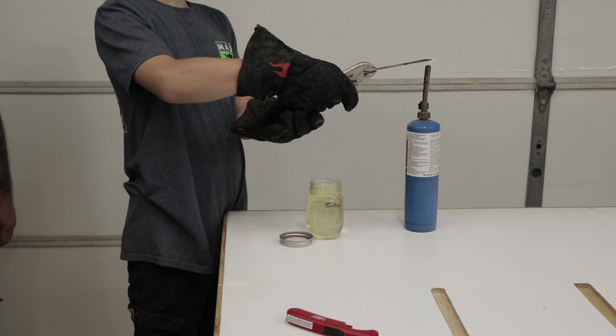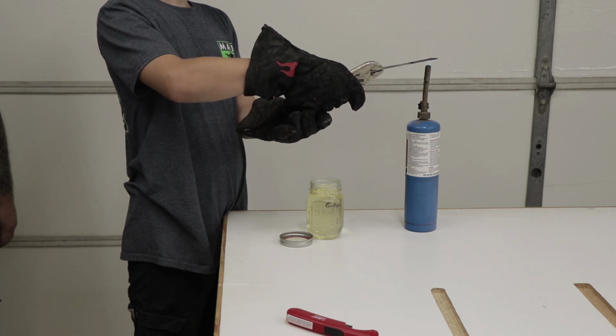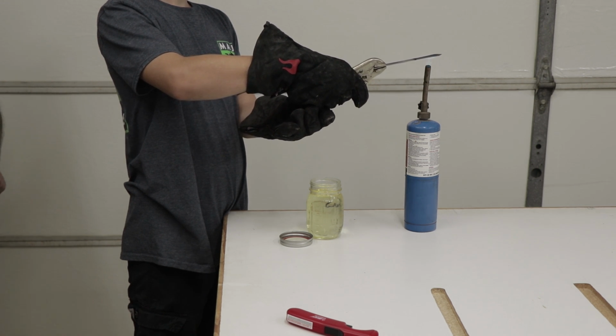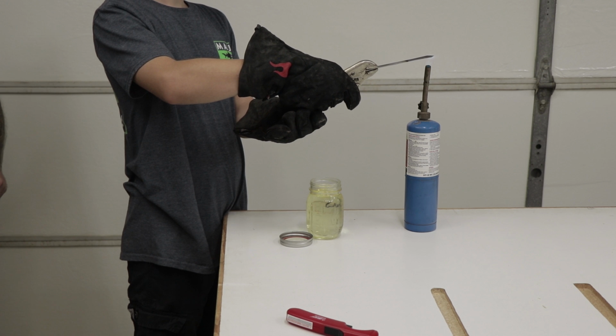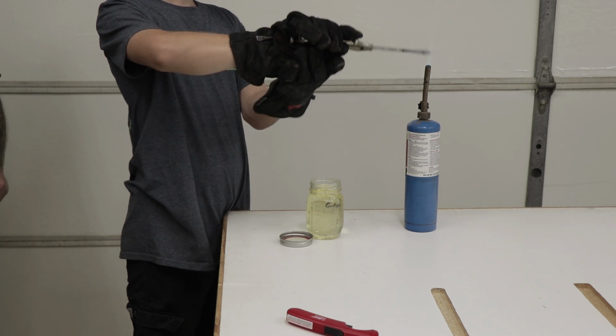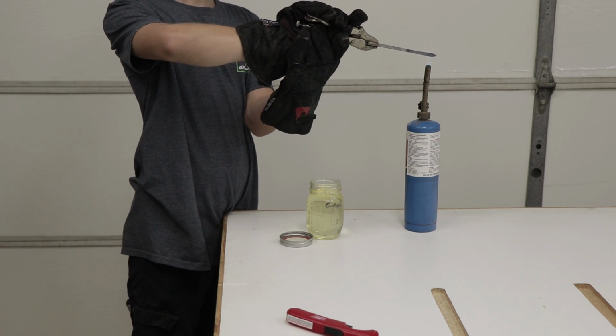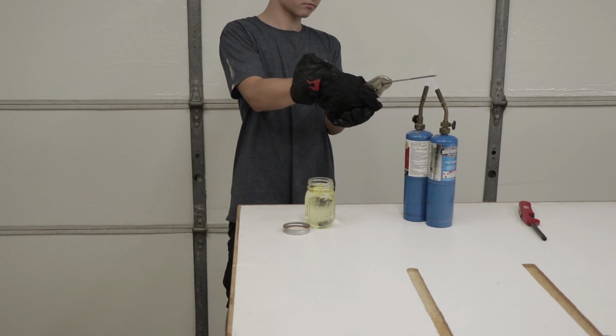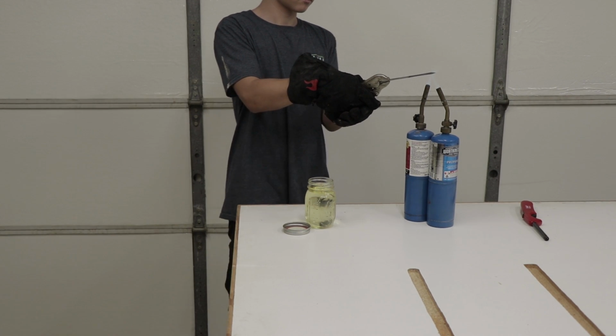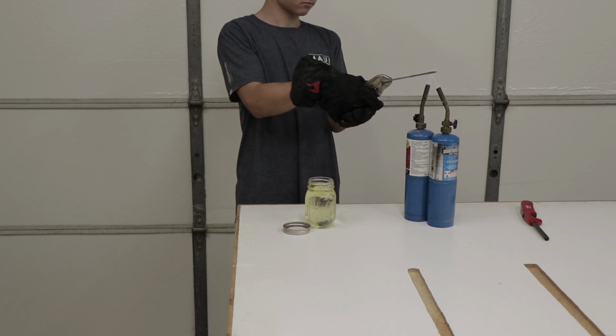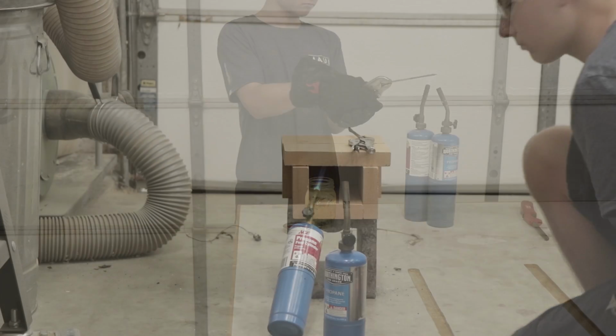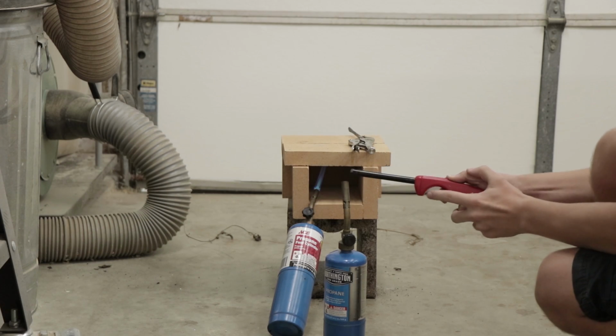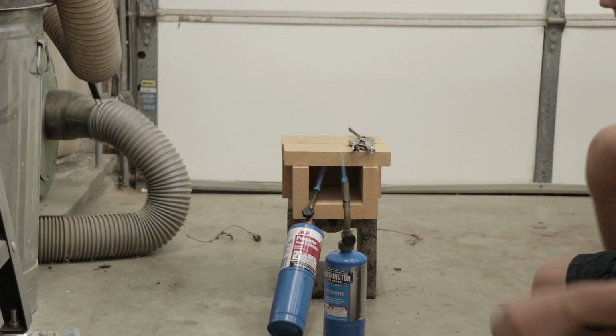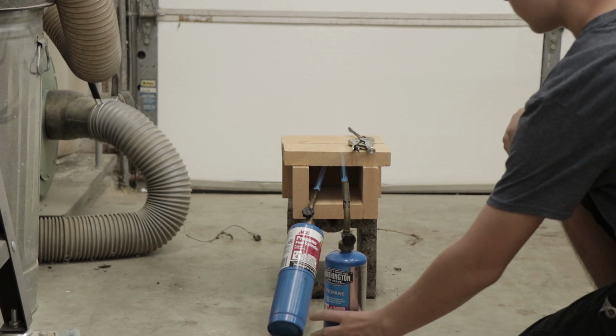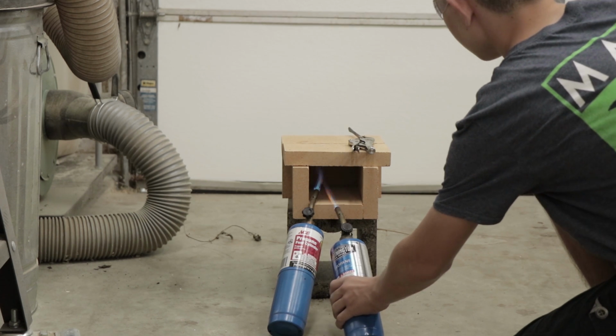Now he was ready to harden the steel. To do this we needed to get the blade to about 1450 degrees, or an orange color, or just above a non-magnetic state. So we first tried heating it up with one propane torch and that wouldn't get it hard enough, so then we tried two propane torches. And when two didn't work, we had to make a little makeshift forge out of some fire bricks and stick both propane torches in there to get the blade to that real bright orange color that we needed.